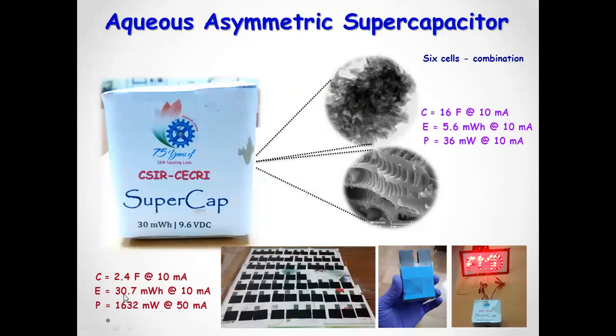You could see this capacitance is 2.4 farad at 10 milliampere. This could be increased to 16 farad where 6 cells are connected. So this device has a total stored energy of 30 milliwatt hour, and the voltage is 9.6 volt. Why 9.6 volt? Since for most of our applications we need a minimum 9 volt battery. The prime idea is to replace the 9 volt battery with a supercapacitor. That's why we demonstrated this supercapacitor with 9.6 volt.